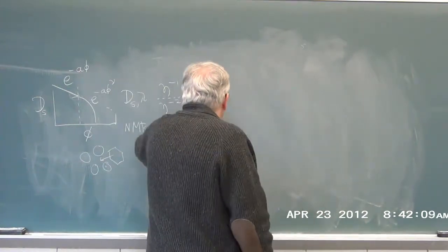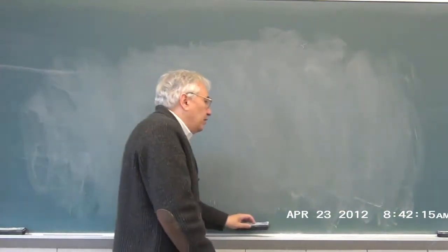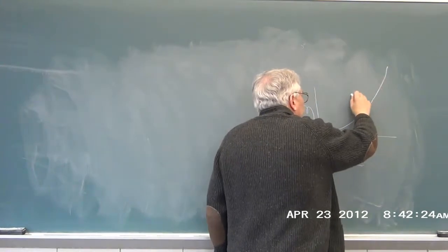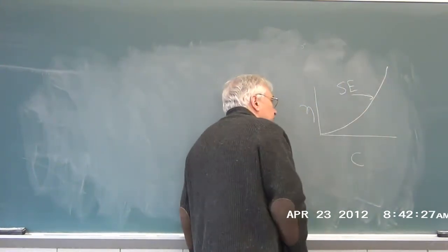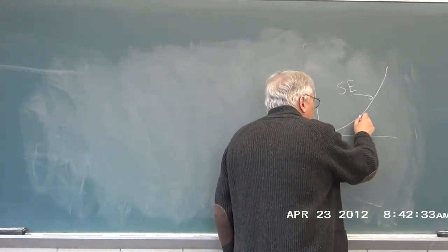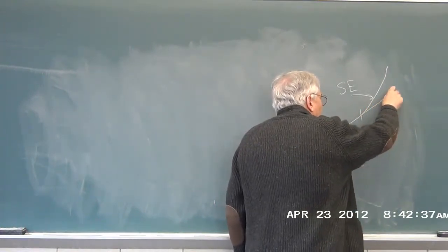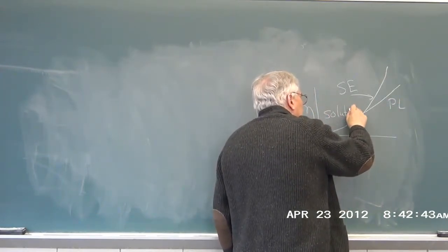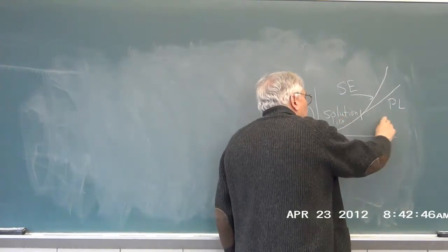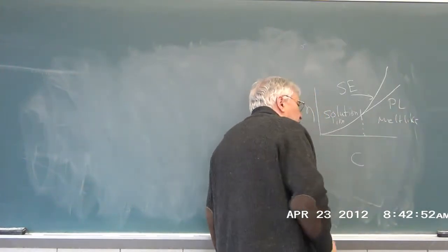If we look at the zero shear viscosity, the low shear viscosity, we found that some systems, but not all of them, do have a transition. That is, there are some systems in which the viscosity is just a stretched exponential in concentration all the way up. And there are other systems in which we have a stretched exponential up to a point. And then we have something that is very clearly a power law. This is the solution-like, melt-like transition. It is quite sharp.